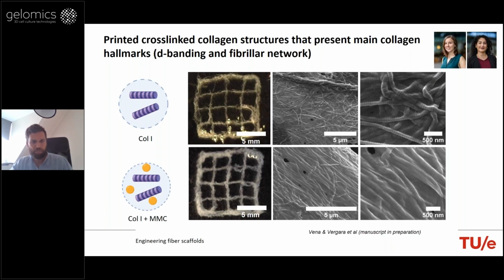And what we also observed is that independent of the presence of the crowder, we could print collagen that showed the main hallmarks of collagen. So basically the D-banding structure and the fibril network, which is typically not trivial to achieve when we start from simple diluted collagen molecules. So we can now process collagen and achieve the main characteristics of collagen, being the D-banding pattern and the fibrillar network, and with the presence of macromolecules, or in this case a synthetic polymer PEG, we could further densify and achieve some sort of more aligned printed threads.